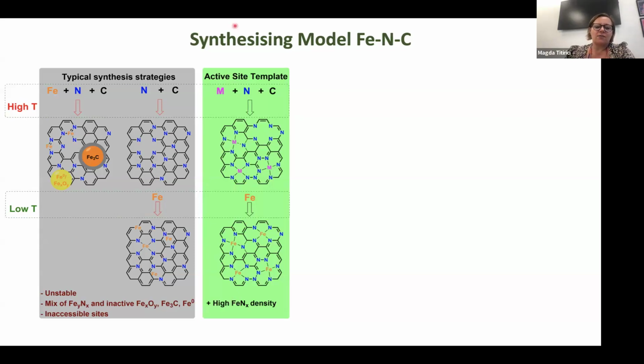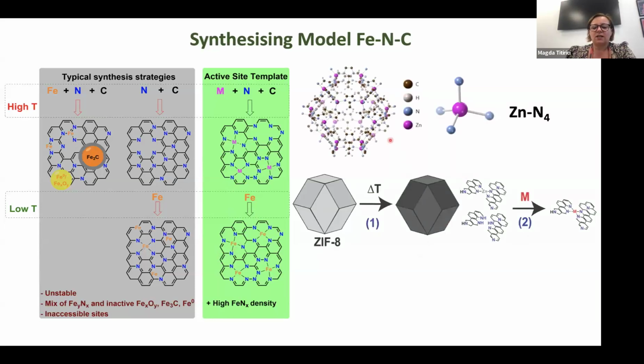Now, another way of doing it is to start with a precursor that already contains this configuration of a single atom coordinated to nitrogens. There are many examples, porphyrins and so on in the literature. And then you could exchange this metal for your metal of choice, for example, iron. In the literature, people use a lot of ZIF-8. The ZIF-8 has this right configuration of metal coordinated to these nitrogen sites.